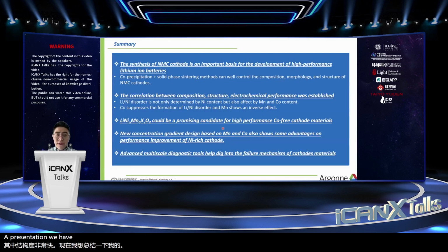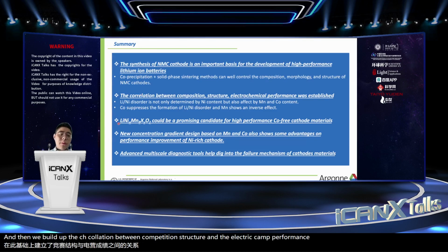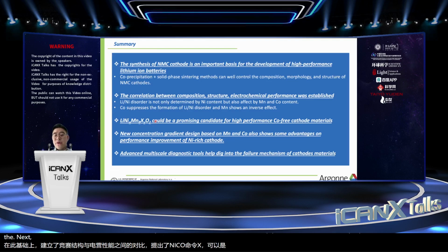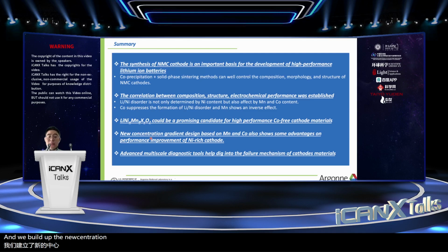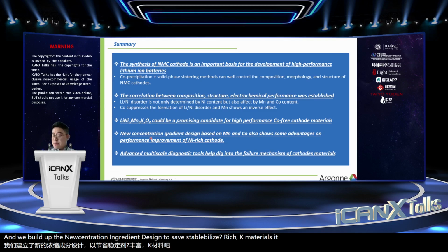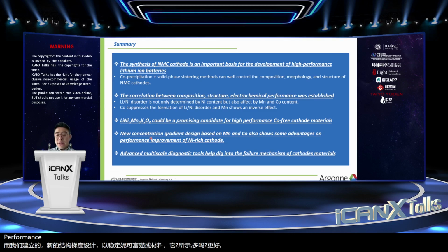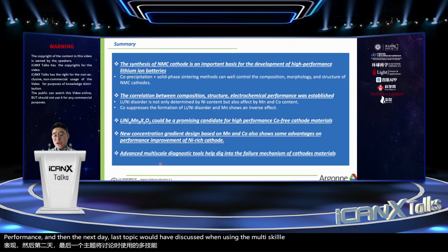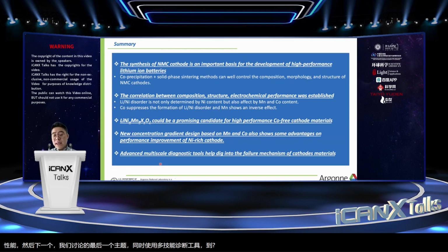We have built up the synthesis capability for most of our NMC cathodes, and then we built up the correlation between composition, structure, and electrochemical performance. We further propose that nickel manganese X can be the next generation cobalt-free cathode, and we built a new concentration gradient design to stabilize nickel-rich cathode materials. It shows much better performance.